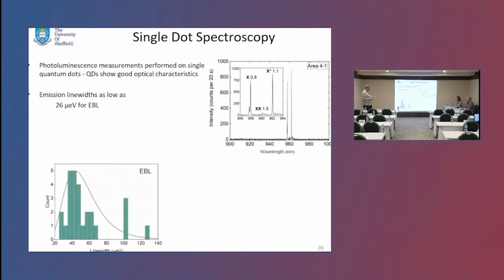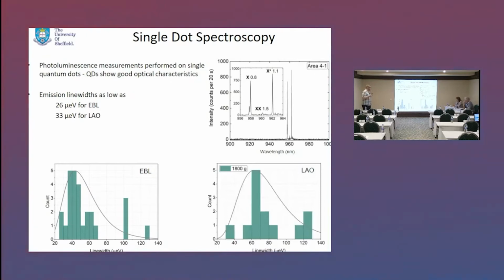So again, shoving things at the bottom of the slide, a distribution of line widths that we've measured for E-beam for effectively a small number of arrays. So we have a modal line width that's around 40, but our best line width is approaching our resolution limit of our spectrometer, which is about 20 microeV. So it's possible that if you look at enough arrays, you might find dots which are even narrower line width than that.